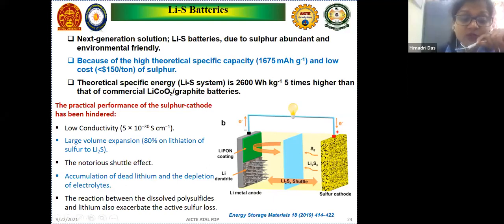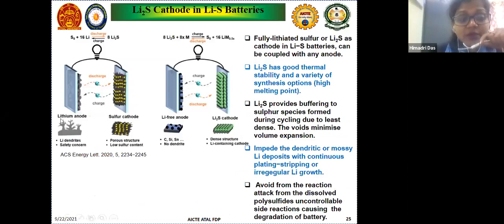Apart from that, there is also dendrite formation as well as dead lithium formation during the charge discharge. They also suffer from polysulfide formation, which causes loss of sulfur. So the coulombic efficiency is again reduced when there is reduction of sulfur in the system. Here we can see when we use the lithium anode, there will be dendrites in the lithium anode, and when we use the sulfur based cathode, the sulfur content is less, and the charge discharge will reduce. But interestingly, when we use a lithium free anode, like some carbon or silicon, the dendrite formation will be less, as well as when we used